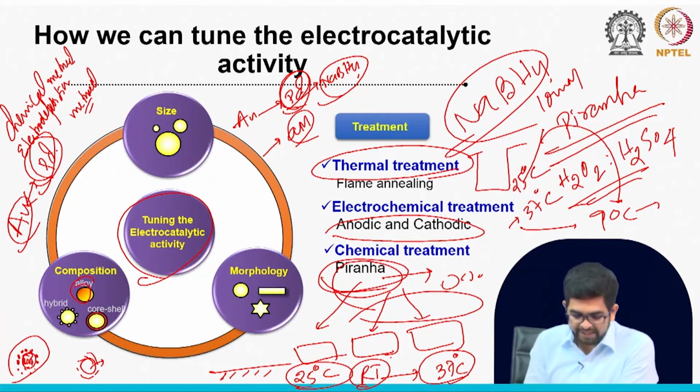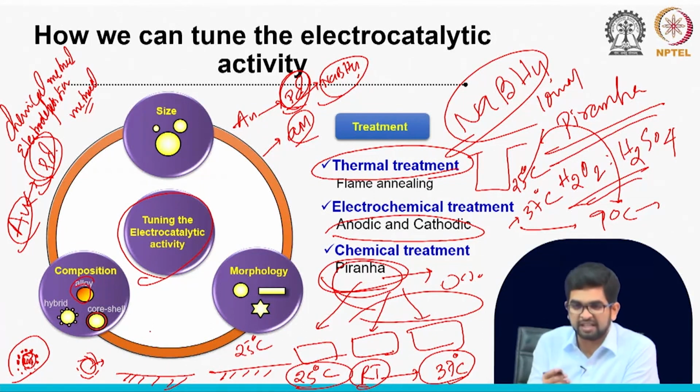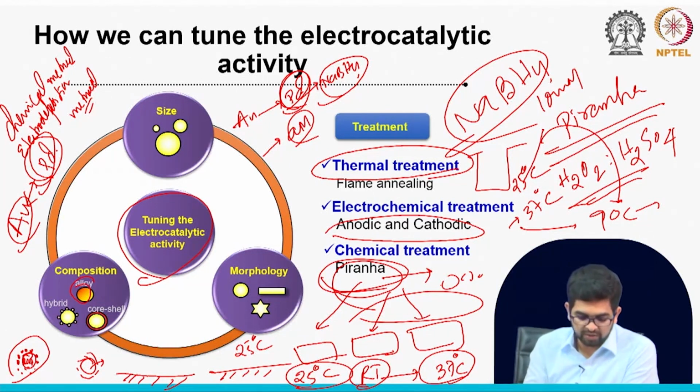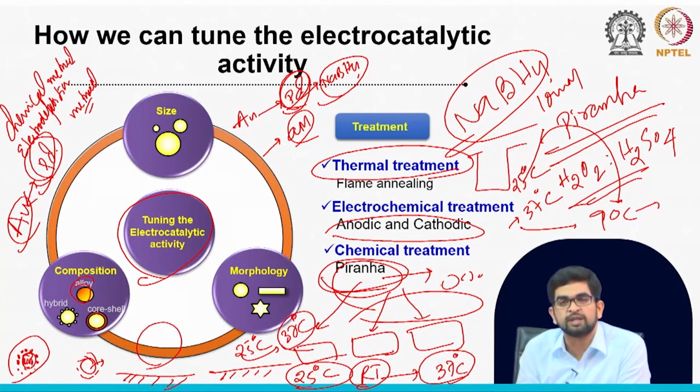Control experiment means, suppose you have the electrode surface at room temperature, 25 degrees Celsius. You can check the cyclic voltammogram of your sensor surface using the basic substrate, without biosensor modification. Then increase the temperature to 37 degrees Celsius using the same basic substrate and check the cyclic voltammogram.